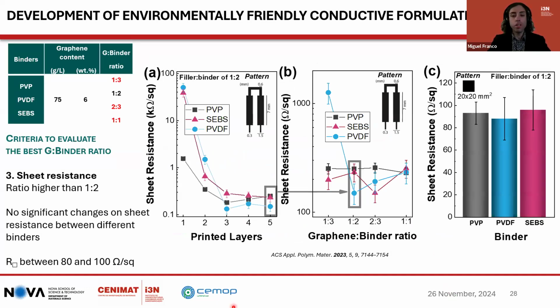The final criterion was to evaluate the sheet resistance of the films. You can see that for higher binder ratios above 1 to 2, the sheet resistance stabilizes, meaning that these formulations are well above the percolation threshold. There is no significant change in sheet resistance between different binders, with sheet resistance between 80 and 100 ohm per square. I have to highlight that these results were obtained using low temperature thermal annealing, under 120 degrees Celsius, which allows printing on a wide array of flexible and temperature sensitive substrates. By exclusion, the ratio of one graphene to two of binder was selected.